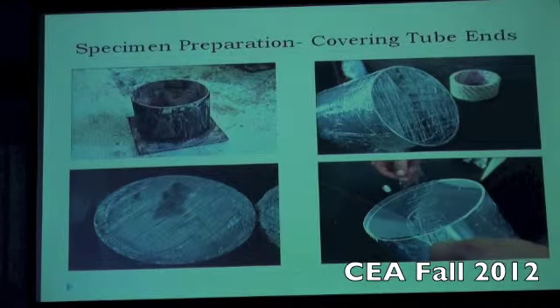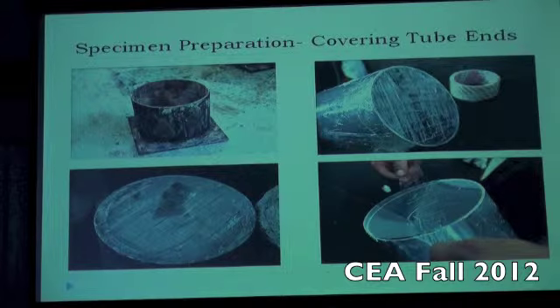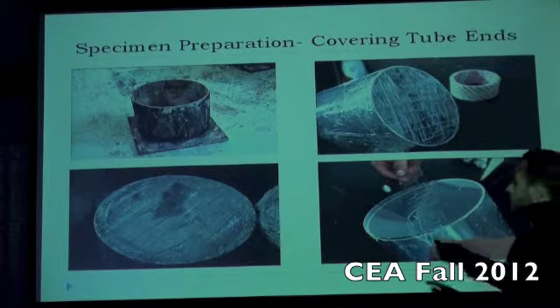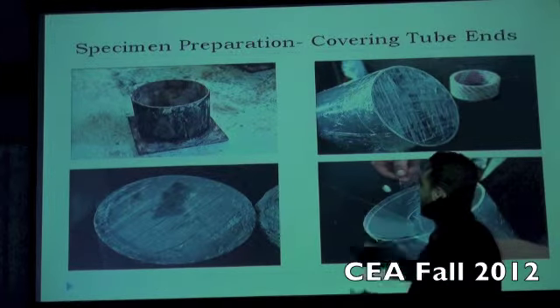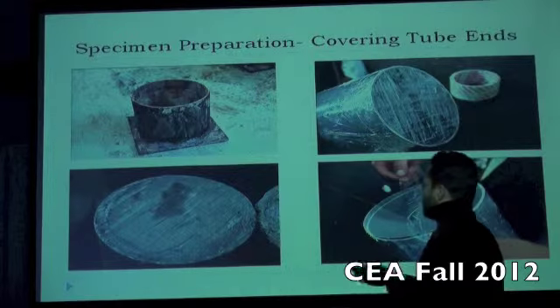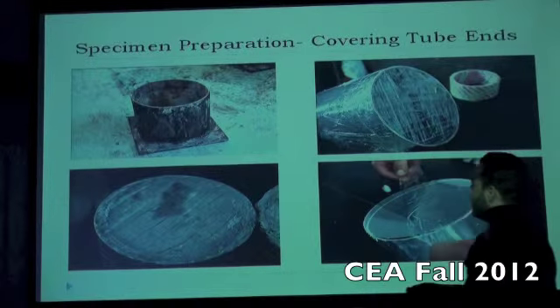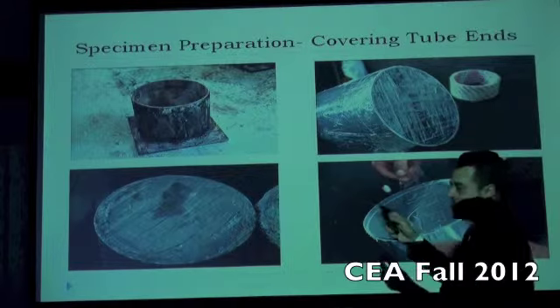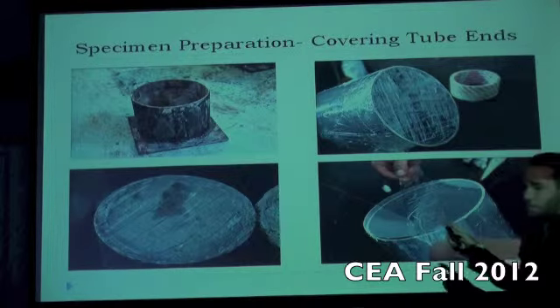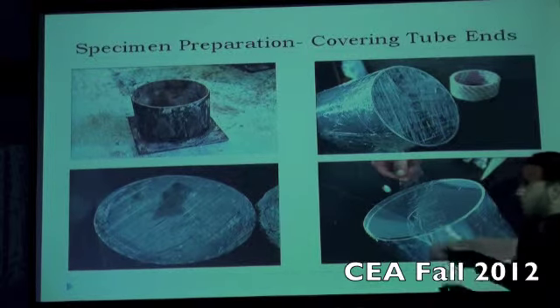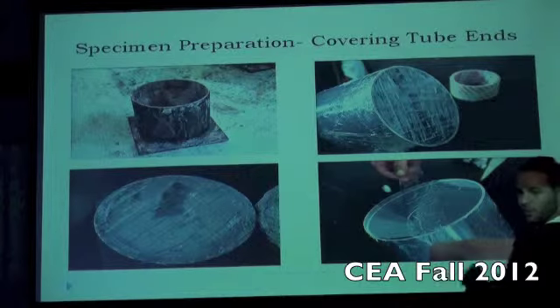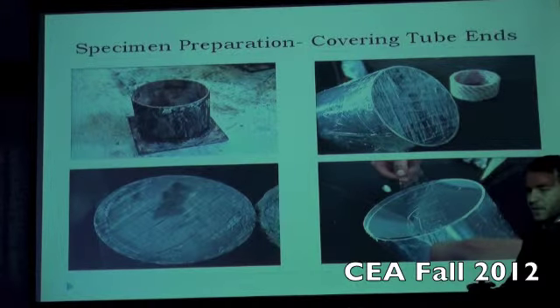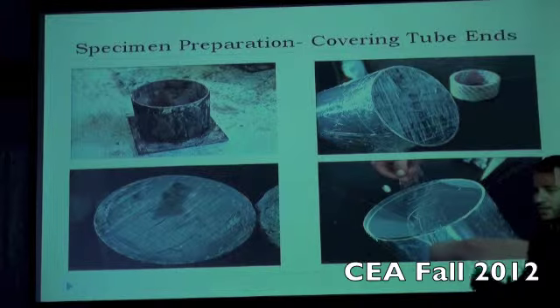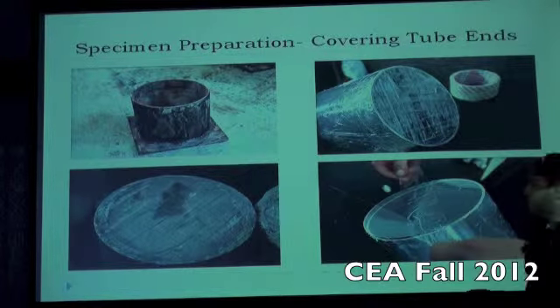Here are some tools we used while casting the pipes. This is a steel end for the pipe to avoid the concrete from going out of the pipe. We use it at first, and then we had some problems with it, because when we put the sample out, it was broken because it was very tight on the pipe. So while removing it, there were cracks in the concrete.